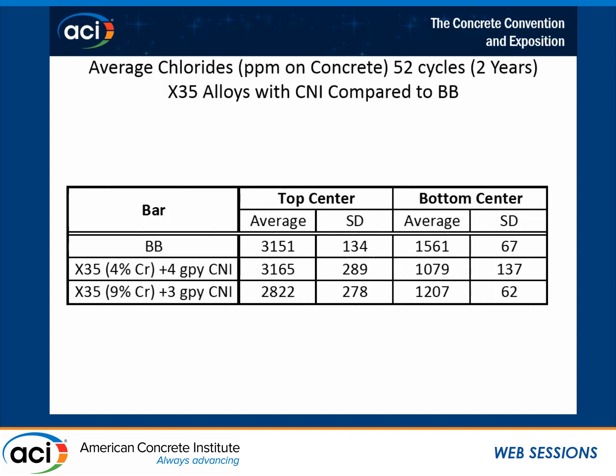And once again, you can see a tight standard deviation coefficient. With calcium nitrite, you can see a significant drop in both cases relative to control with these standard deviations. This is statistically significant to probably a 95%. I didn't do the exact analysis, but I think it's probably close to 2 times the standard deviations on each of them, and they don't overlap. So this is probably significant to close to a 95% confidence limit. So you can see that it doesn't matter what type of bar you have and what you do to the concrete, you can reduce chloride from moving farther down.